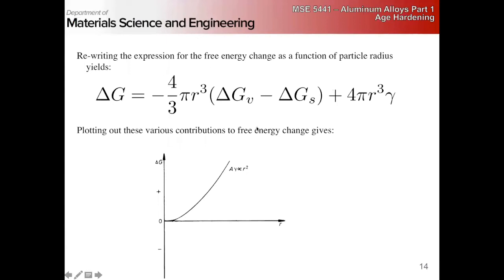So if we look at it, we can rewrite this expression for the free energy change as a function of the particle radius, right, instead of volume, right? And that's a typo. That should be squared. Surface energy, surface term, surface energy is squared, not cubed, right? So our surface energy goes with the r squared. So this adds a positive component to the Gibbs free energy, right? So this is going to oppose nucleation,